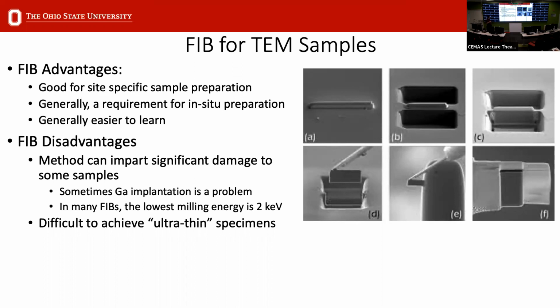Disadvantages of FIB are you can impart significant damage to some of your samples based on the effects of the gallium implanting into your sample. In many cases, the lowest energy you can go to clean your sample in the FIB is 2 keV, which is much higher than what you could with argon. And I'll give an example later, but there are improvements being made nowadays to get ultra thin specimens, but that is still a challenge for some cases.